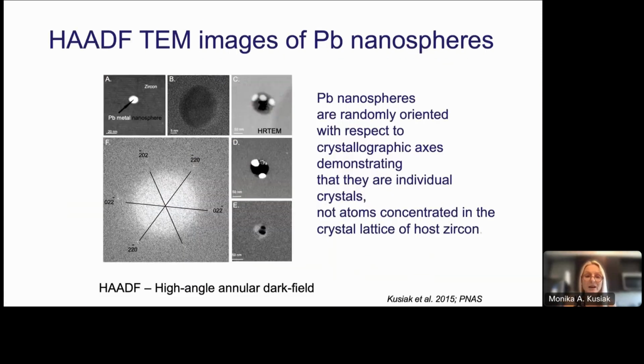So when we analyzed those grains, I have to tell you that we were really shocked when we found out that lead is in a pure metal lead state. So we had no lead silicate, no lead oxide, no lead sulfate. I mean, having so much oxygen and silica in the area, it was pure lead in the zircon, and sometimes this lead was completely alone, a metal lead nanosphere in zircon, and sometimes it was clustered, or had tiny droplets of lead.